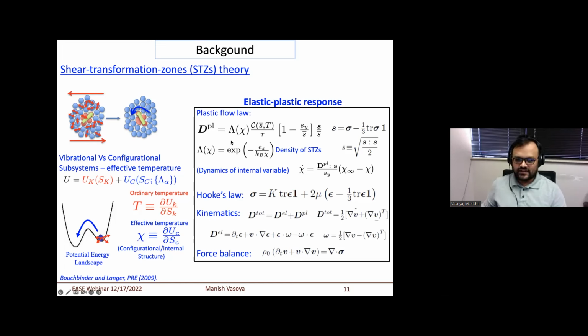So the plastic flow mainly depends on your effective temperature chi, because this is what your structure is evolving, right? And the orientation, which is detected here, is through the deviatoric stress tensor. Okay, and then you have this Lambda, which shows the density of the STZs, kind of the Boltzmann constant or the energy, which has an exponential form. And then you have the internal dynamics of that internal variable chi, which represents your microstructure, which is nothing but how much plastic work you input and how the structure is evolving. This is the key, the dynamics of that equation.